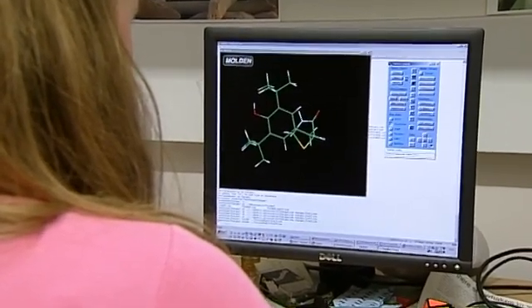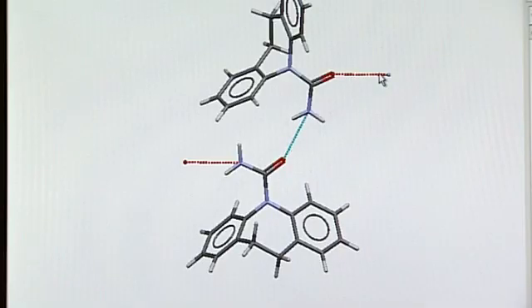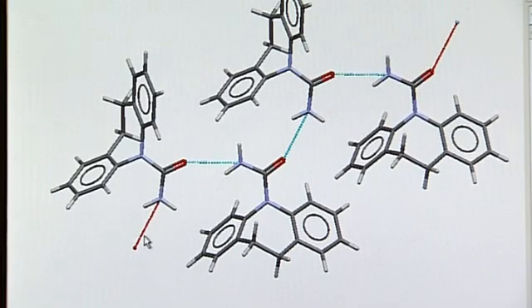For example, a drug that forms as a dimer or a chain — if a pharmaceutical company has developed it and knows it has the crystal structure of a dimer, when you take a tablet it will dissolve at a certain rate in your body and have a certain dosing profile. The fact that it might form a chain one day means if it starts forming this chain in the manufacturing process and you take a tablet of that instead, it has a completely different dosing profile in your body — so you could be overdosing, or it could not be dissolving at all and just going straight through you. Those are the ultimate implications.